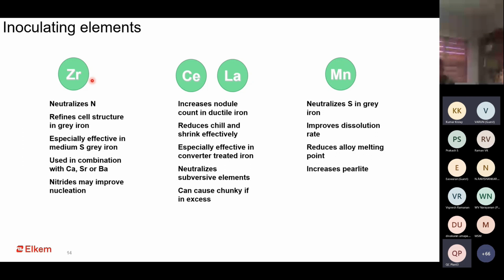It, in combination with zirconium, can give you a very potent zirconium manganese based inoculant, especially for the gray iron, where it works even at a slightly lesser content of sulfur. If for some reason the foundry is not able to maintain higher sulfur, a zirconium manganese kind of inoculant can give you a much better effect there.